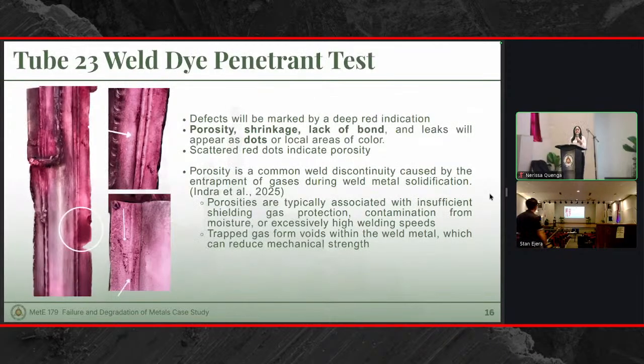Lastly, we conducted dye penetrant tests to determine if there are any noticeable defects, and the red spots, or red dots, that we see are evidence of porosity. Porosity is a common weld discontinuity caused by the entrapment of gases during weld metal solidification. So from this evidence, we can suggest that the initial failure of tube 23 started from weld defects.